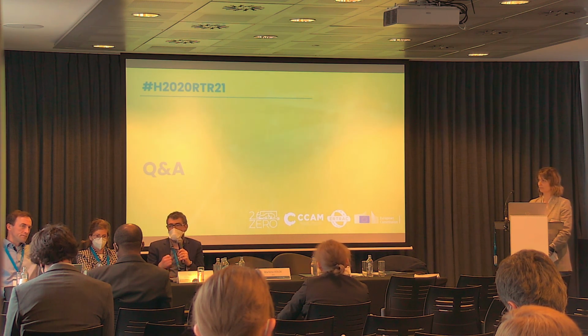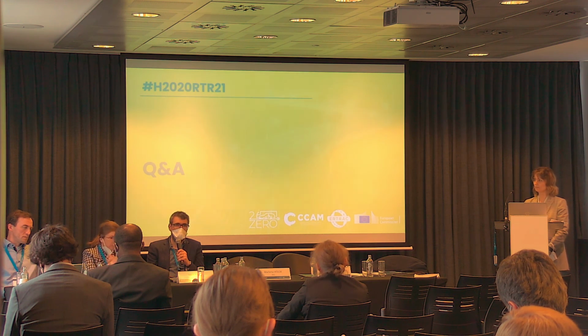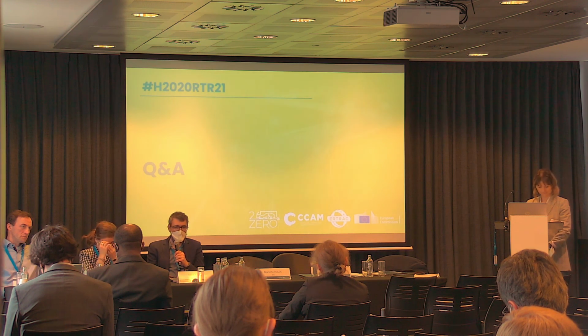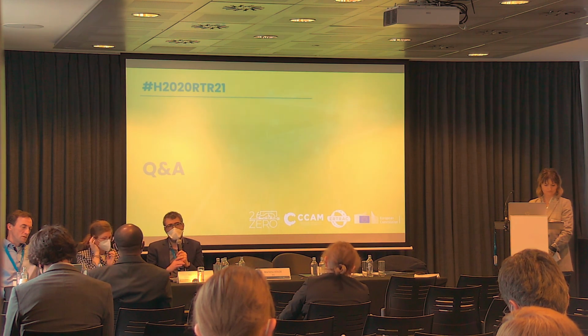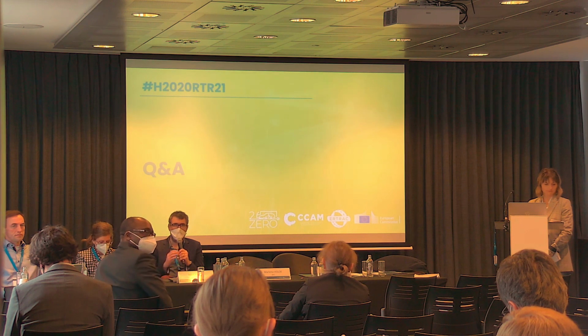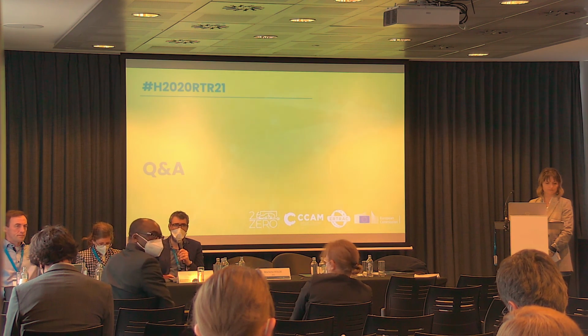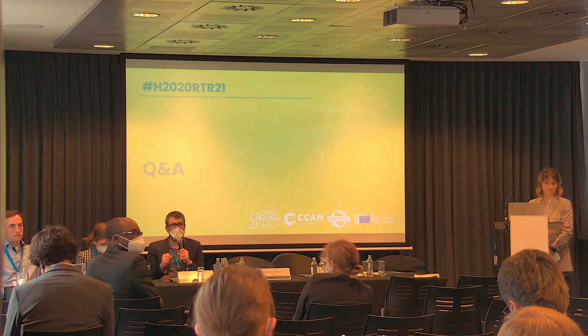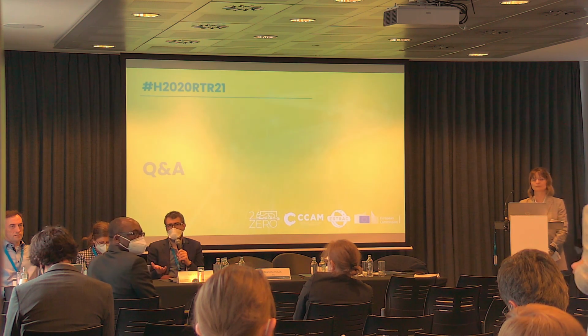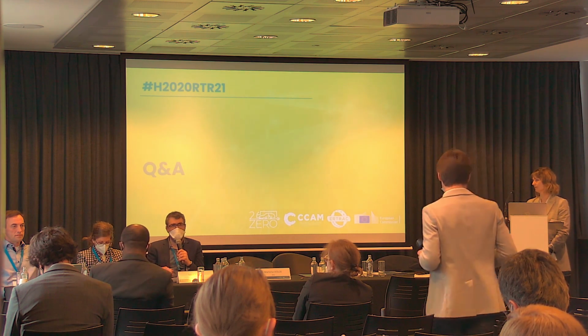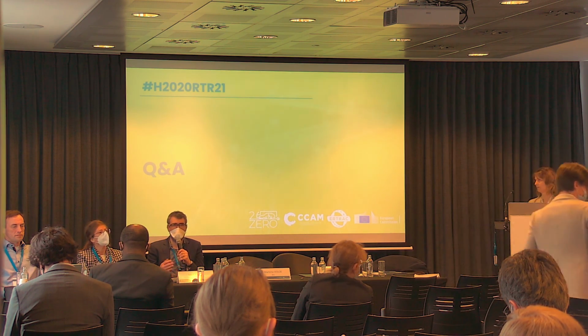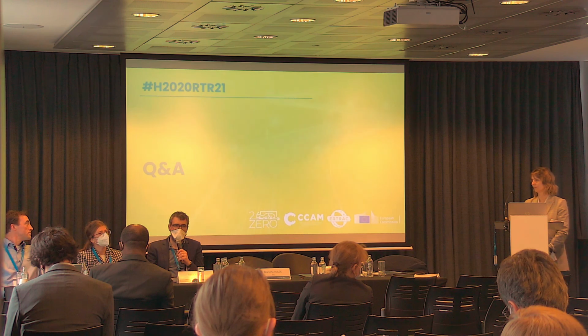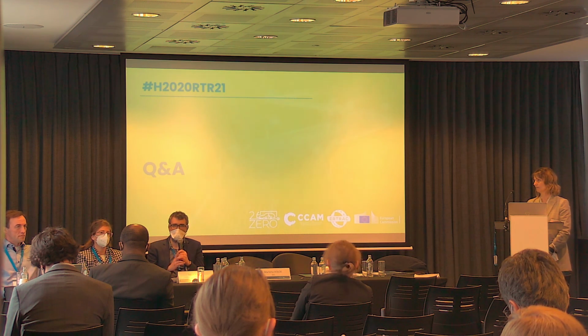But in the end, some parameters are not directly measurable, so it's complicated. We have to make some guesses from what we observe, especially from specific checkups and so on to analyze the aging, to see whether what we make as assumptions are correct or not, whether the aging that we see is compatible with, for instance, loss of active material, loss of lithium inventory, and so on, and relate them to the models.